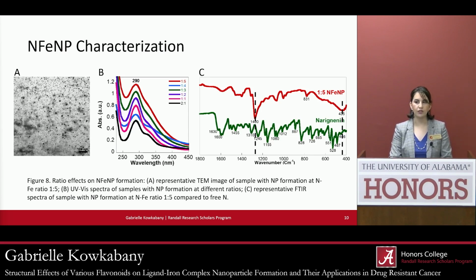And so this is for a 1:5 naringenin to iron ratio of nanoparticles, and you can see that these are the black dots that are in this image. They're around 10 to 20 nanometers in length. And then I confirmed with FTIR spectra that iron coordination did actually occur. And so these are really nanoparticles that you're seeing.